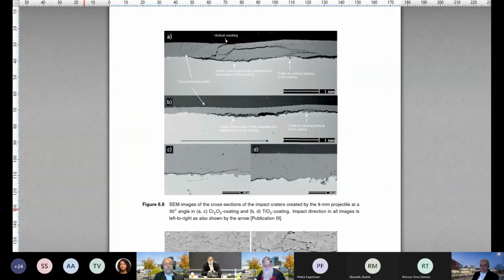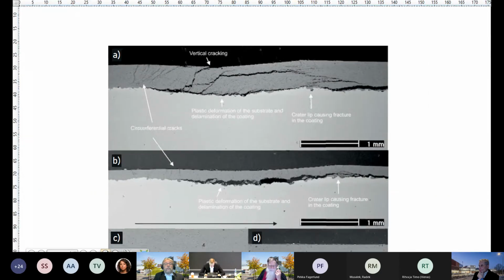Yes, indeed. Here it was a bit of naivety in the beginning to not consider that this test obviously goes to the substrate. As you see, the substrate is deformed. And if we were successful in finding or making a damage-tolerant ceramic coating, it would have a coating that is reasonably intact after all this. So what can I see here? Basically, with the thicker coating, I want to say theoretically that the Hertzian stress concentration depth is within the coating, and that's why we see so much cracking inside the coating, whereas the thinner one is thin enough that the stress goes over it and it stays in one piece, if that makes sense.